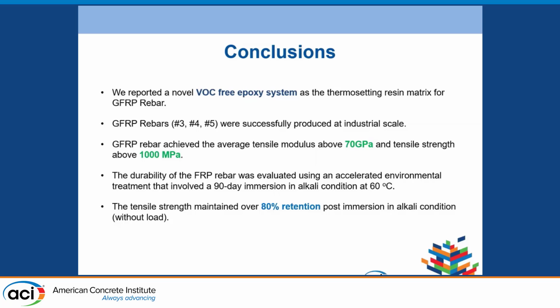The bar is also tested by accelerated testing for corrosion resistance, at 90 days immersion in alkaline condition at 60 degrees C. The tensile strength maintains over 80% retention post immersion in the alkaline solution.